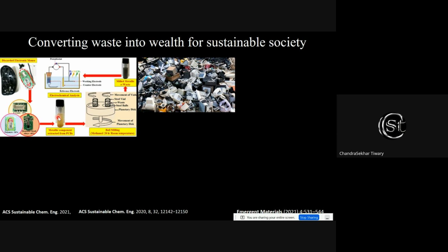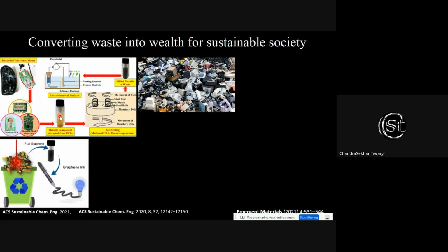We take this powder, put it in water. The moment you put it in water, the metals settle down, and ceramic and polymer remain on the surface. You take this ceramic, take this metal, we can mix it and make a metal composite out of it, and the polymer can be utilized to produce graphene. So these are fine polymer particles; use laser onto these polymer particles, and they become carbon. And these are very conducting carbon, which can be utilized to make any sorts of carbon ink and so on.